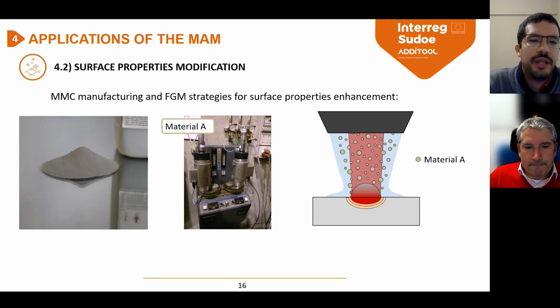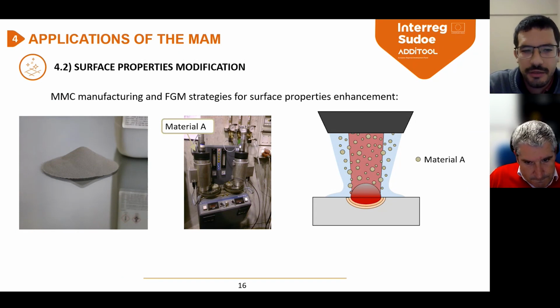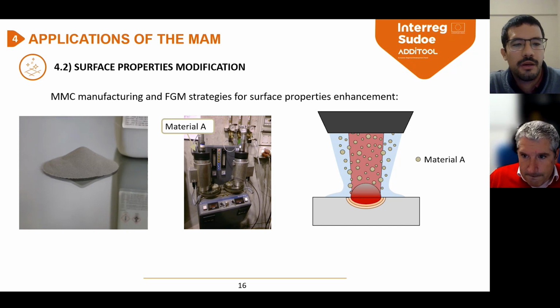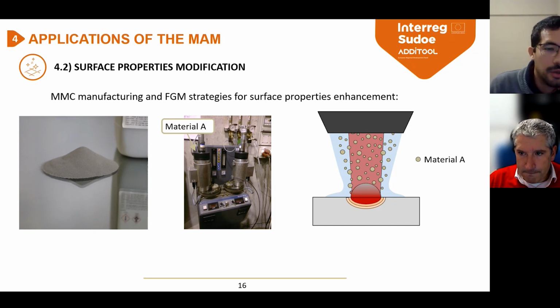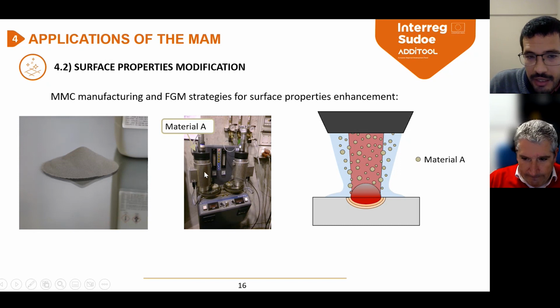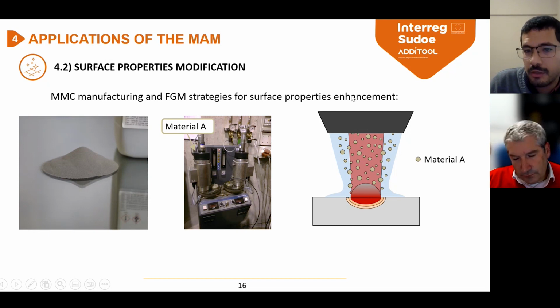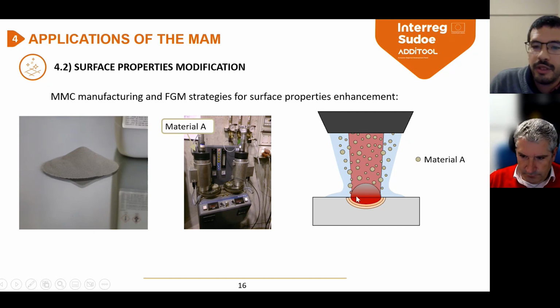The second application is related to the surface properties modification. Traditionally, when we think about the additive manufacturing process, we always think of the filler material, which in the present case is in powder form. We introduce this material in the powder feeder. In our case, it's a gravimetric powder feeder. We introduce it inside, and it falls down thanks to gravity. We have a rotary plate, and by controlling the velocity of rotation, we control the feed rate of the powder that comes from this pipe to the nozzle, and we inject it into the melt pool in order to obtain a clad made with material A.